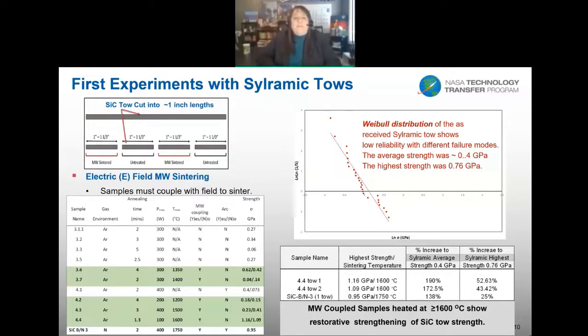So I think part of the heating process is that there's going to be a limit, and it depends on the constituents. So in the ceramic and also in the Tyranno, they both have, I think, titanium in them, and it could be that that's reacting and aiding in sintering, or the boron, because they have those sintering aids. So in the case of the Hi-Nicalon S, where it's much stronger already to begin with, we didn't see that high jump, right?